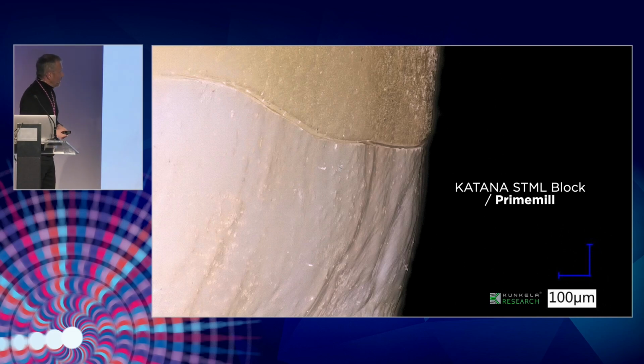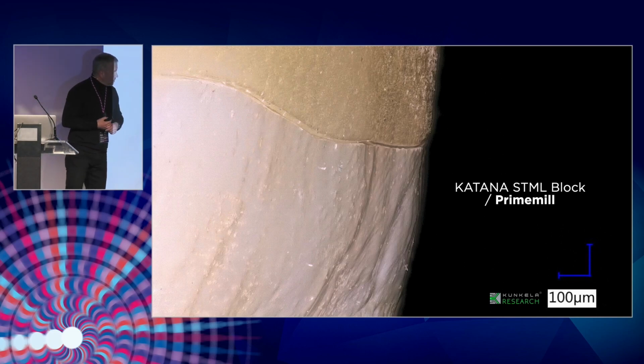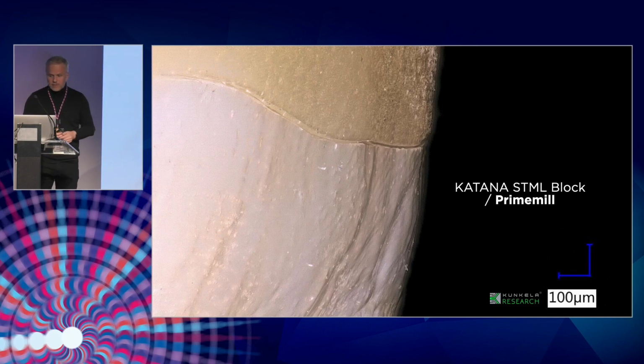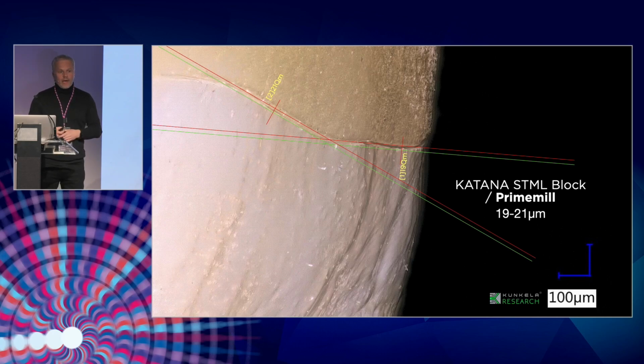And you can see here zirconia manufactured by Kuraray Noritake. It's a brand name Katana, 19 to 21 microns. It's really great results. We can be more precise because we are on this border, 20 microns recommendation. And it happened thanks to the workability of the material for the milling, and also because everything is milled almost 30% bigger when we use the same instruments. That's why the whole surface has more details, more beautiful, has a higher anatomy, and also avoids the chipping around the margin.